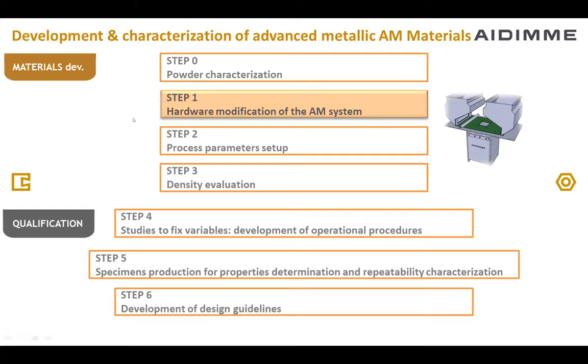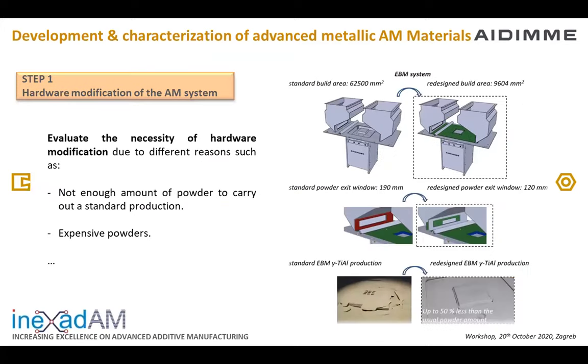This point I said before is optional, but for example, you can perform a hardware modification due to different reasons, such as maybe not enough amount of powder to carry out a standard production, or you are working with expensive powders. For example, in this case, I show you this picture because we work with an expensive powder, a titanium aluminum powder, and we wanted to perform a reduction in the build area of the EBM technology. So finally, we achieved a reduction up to 50% of the usual amount of powder. So at this point, maybe it's interesting depending on the material to process and the technology selected.